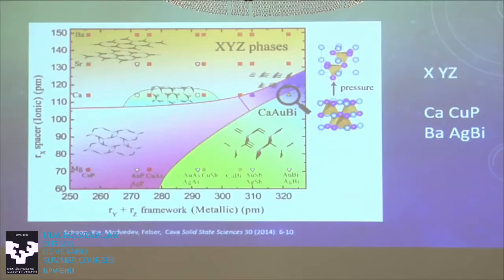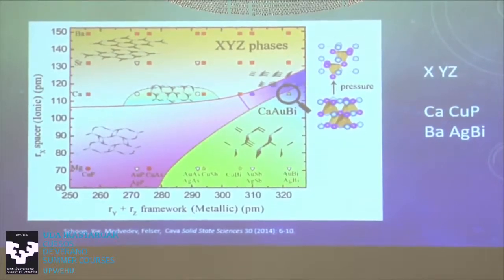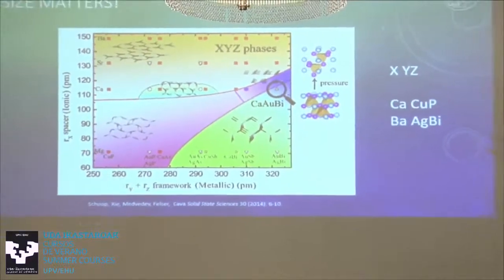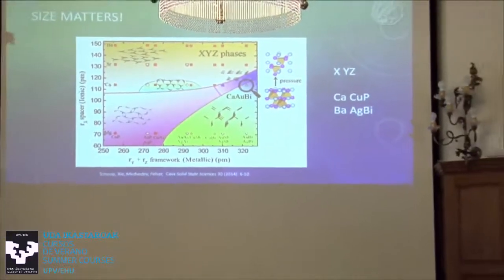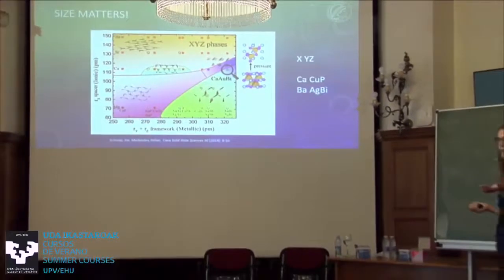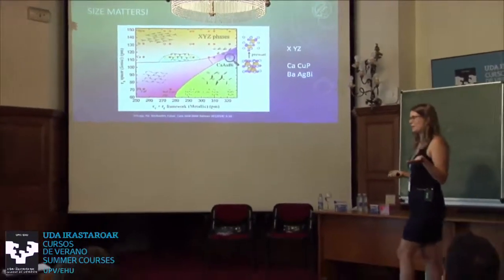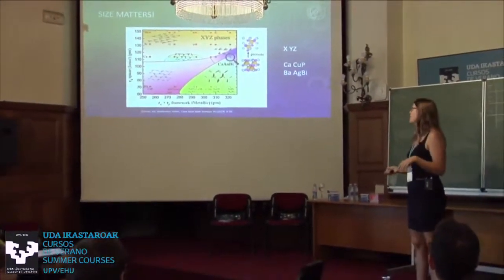And then you see that there are clear regions where the structures are different. Okay, so it really matters. So the ratio of the radius really matters. They can have completely different structures. And then also some of those structures are semiconductors with large gaps, and others are semi-metals with really overlapping density of states, pockets, and everything. And this is dependent on the structure. So it's not only electron counting, it's also size that matters.